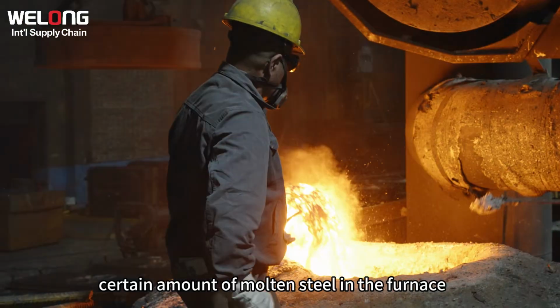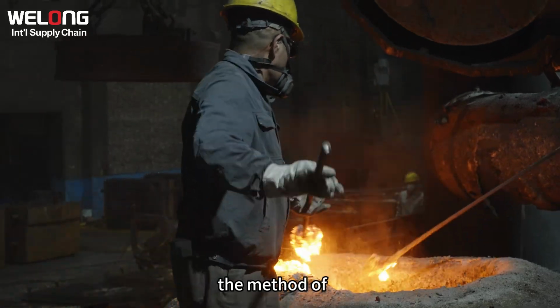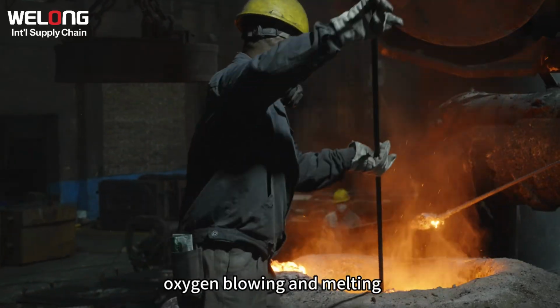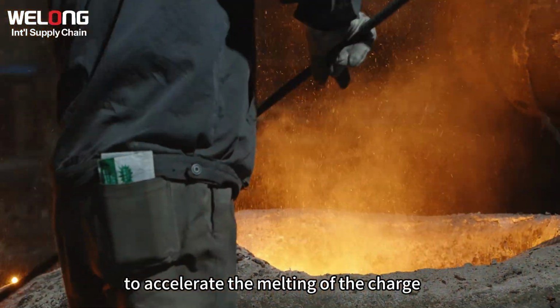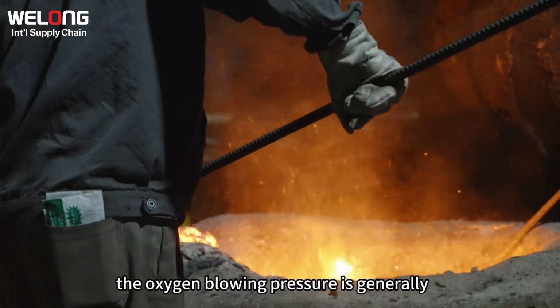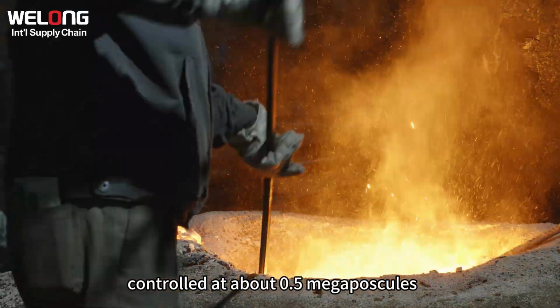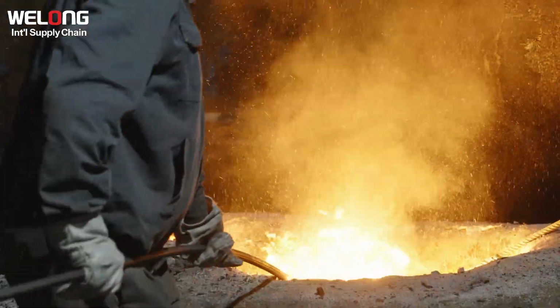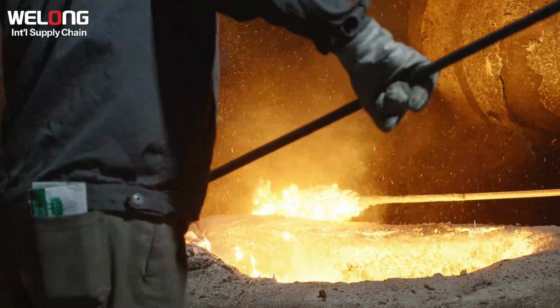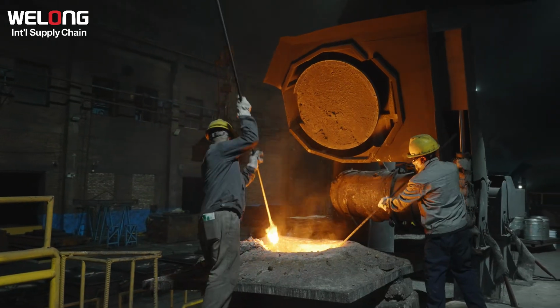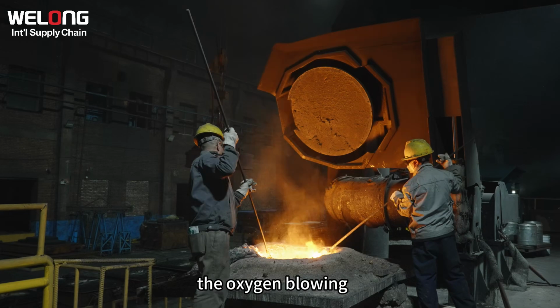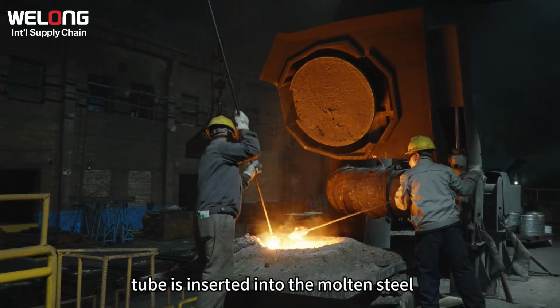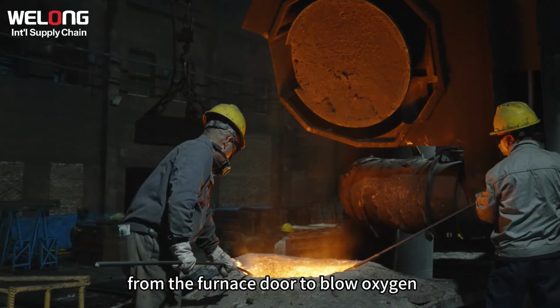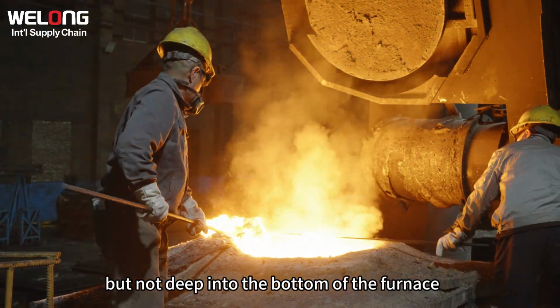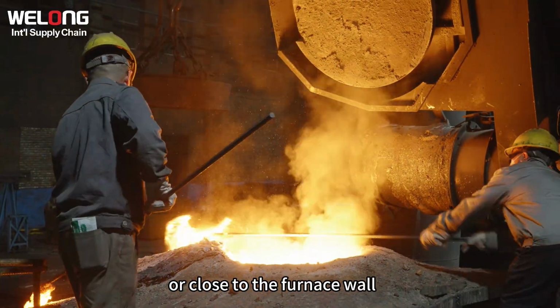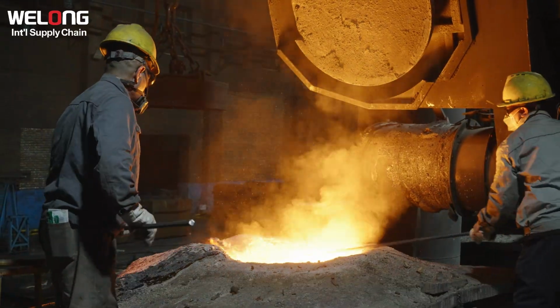After there is a certain amount of molten steel in the furnace, the method of oxygen blowing and melting can also be adopted to accelerate the melting of the charge. The oxygen blowing pressure is generally controlled at about 0.5 megapascals. The oxygen blowing tube is inserted into the molten steel from the furnace door to blow oxygen, but not deep into the bottom of the furnace or close to the furnace wall, to prevent damage to the furnace lining.